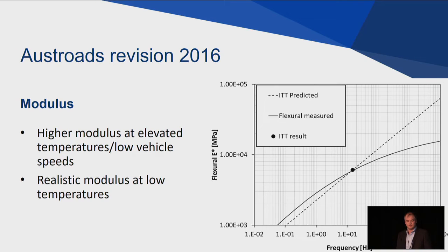What I've shown in this graph is the resilient modulus result, so that's the dot, and then the predicted resilient modulus at different load frequencies, as it used to be done in the Austroads design method. That's the dotted line, the straight dotted line. And compare that to the flexural measured modulus, which is the continuous line, and you'll see that at the lower loading frequencies or the higher temperatures, you get a higher modulus, which corresponds to thinner pavements.